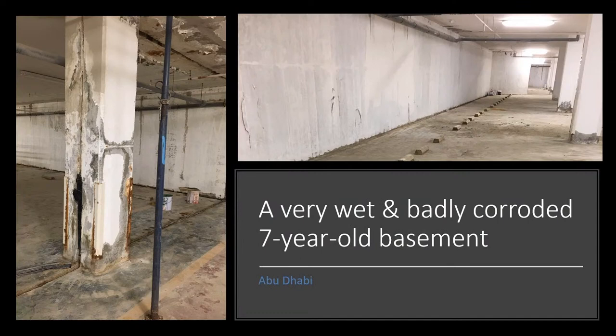Another picture from my Abu Dhabi days, this is literally a seven-year-old basement when these photographs were taken. The waterproof membrane has failed. The water that's getting in there is highly saline. It's causing massive corrosion, cracking, and general leakage in just 7 years.